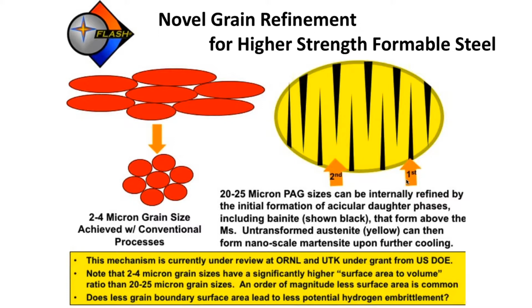What they did is they cut up the other half of the sheet that we did not process, and they did their very best to try and match our strength. And they could only get 1350 megapascals UTS. So it's just kind of anecdotal data, but if a major mill who knows what they're doing could not match our strength, there must be something interesting and special about the process.